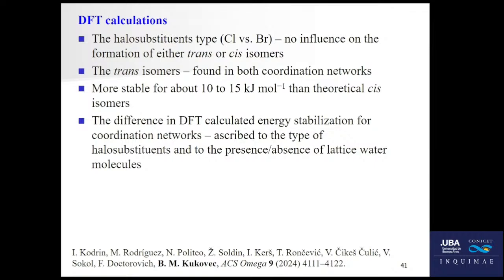And we also calculated energy stabilization for the polymers and the effect of halogen substituents, and in general we concluded that the different DFT calculated energies can be ascribed to different halogen substituents and the presence or absence of lattice water molecules in the structure. And for the methyl and fluoronicotinate, the DFT calculations are still ongoing.